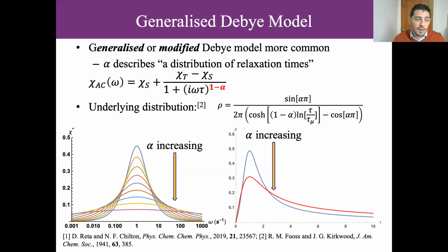And of course, there are competing relaxation processes that happen, different fundamental spin-phonon interactions, or quantum tunneling or whatever. But all of those should be combining, because those are all very fast processes. The spin-phonon collision rates, so the tau naught that sits in front of this, is on the order of 10 to the minus 10, 10 to the minus 12, right?